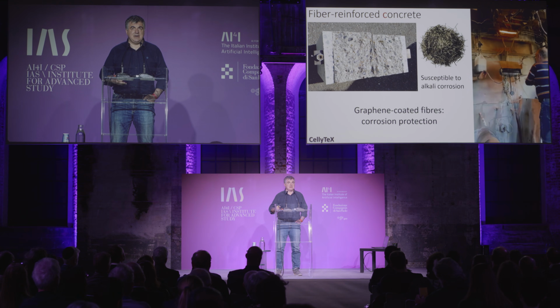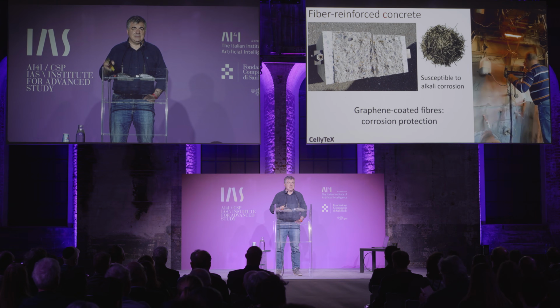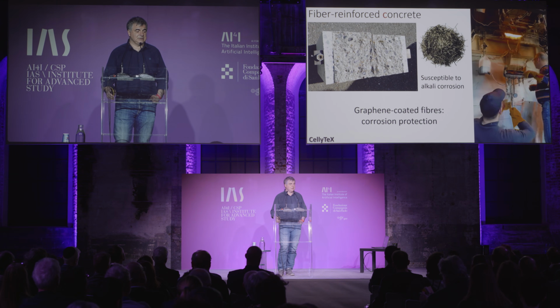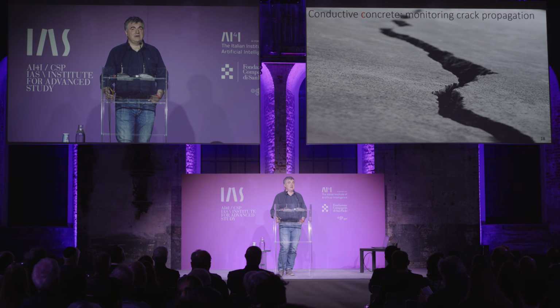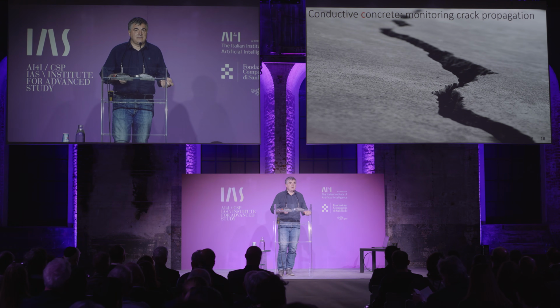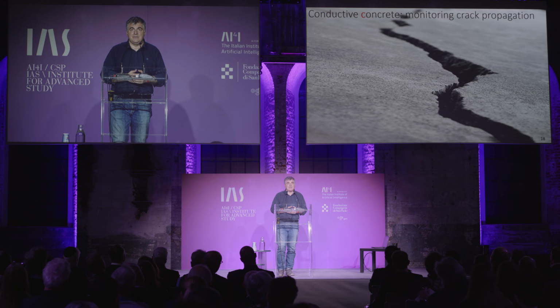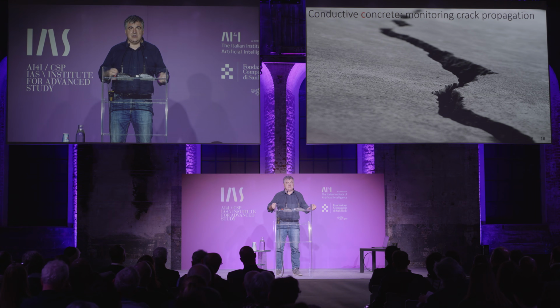So the expected lifetime becomes at least five times longer than if you don't coat it with graphene. And then, because we can put quite a lot of graphene and quite a lot of this fiber in, your concrete starts to be conductive, and so it's really good, for example, for crack monitoring and failure monitoring, because you can simply measure the resistivity of your concrete slab. It is sensitive to internal cracks as well, so it's extremely good for monitoring failure. And even more interesting, because we can make it conductive, we can turn our concrete slab into a battery.